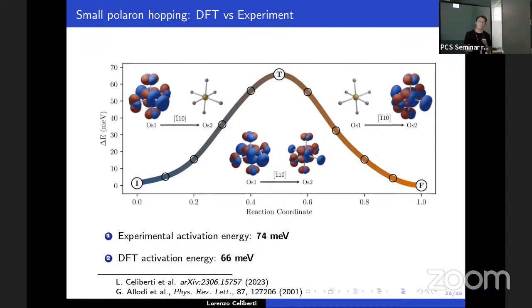Does the polaron structure remain the same all the way? No, so basically you have the polaron structure at the initial point and at the final point, and this is symmetric. Usually you have the same kind of distortion, but then you interpolate the two structures. So at the middle point, you have something in between the two configurations. The distortions are a bit smaller here, a bit larger here, and you have this kind of intermediate situation.